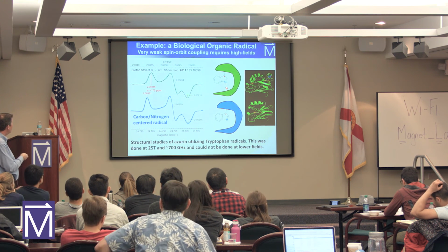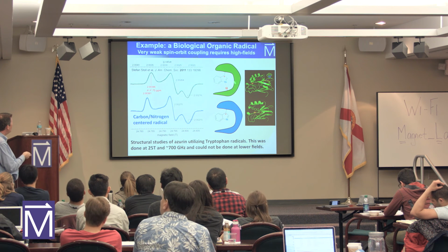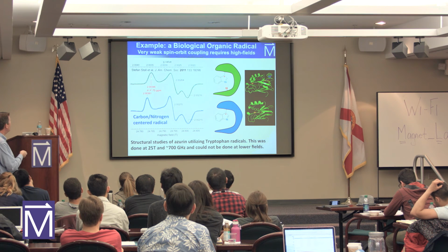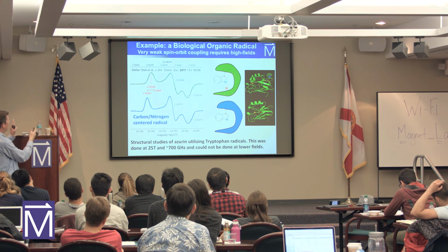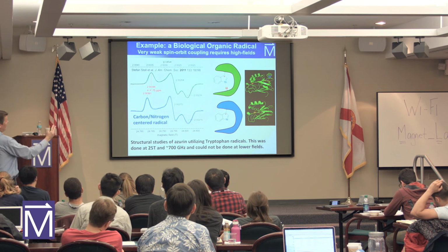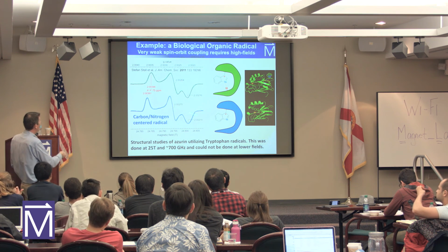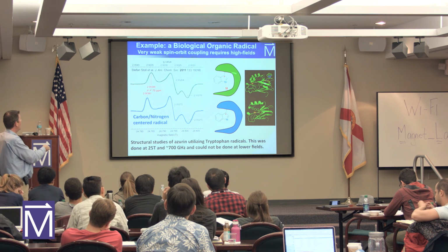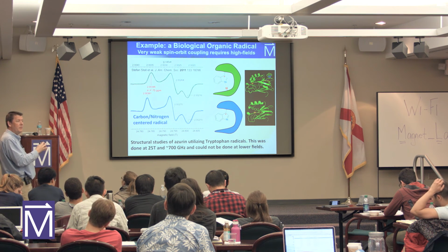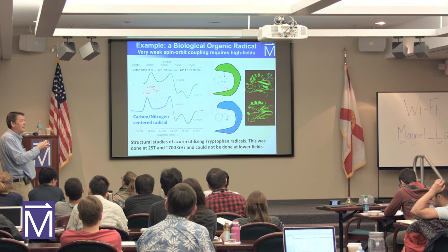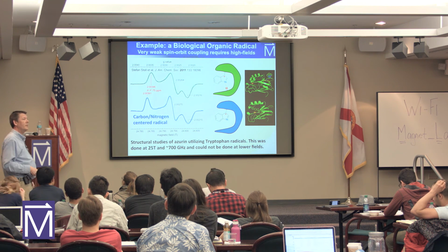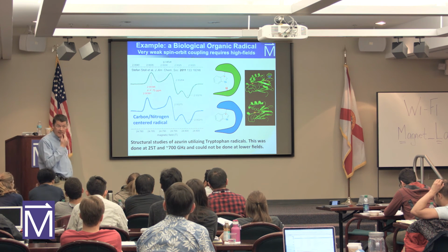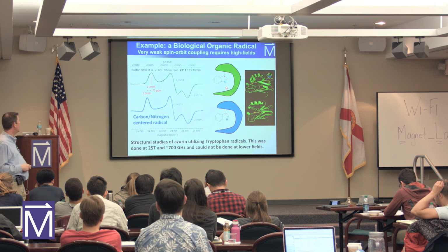And it's a very simple way to see this. When you form this hydrogen bond, the electron becomes even more delocalized, so it behaves more and more like a free electron, so its G-tensor becomes even less anisotropic, it's even less spread. When the hydrogen bond goes away, the G-tensor spreads out because you're essentially localizing that electron on the organic molecule. So almost like the uncertainty principle, by localizing it in space, its anisotropy becomes larger. So these are real heroic experiments that could only ever be done at the magnet lab.